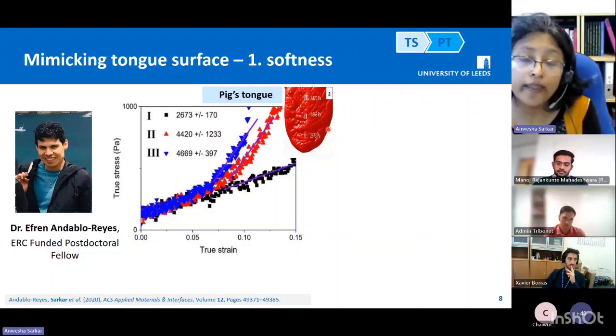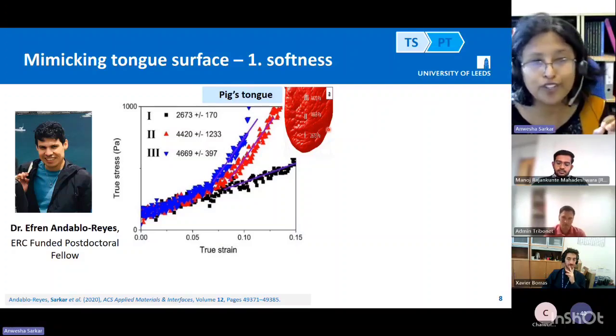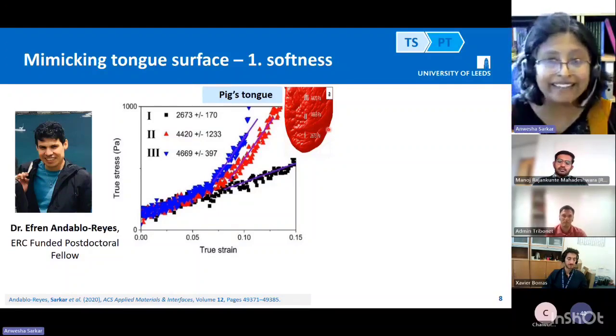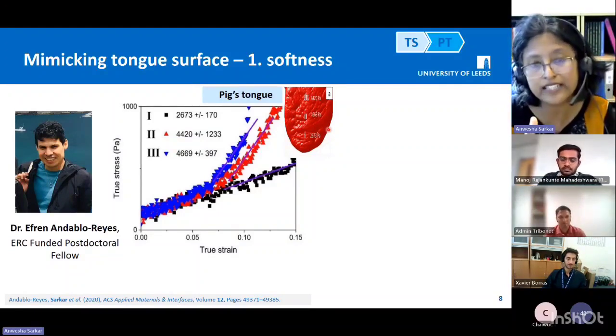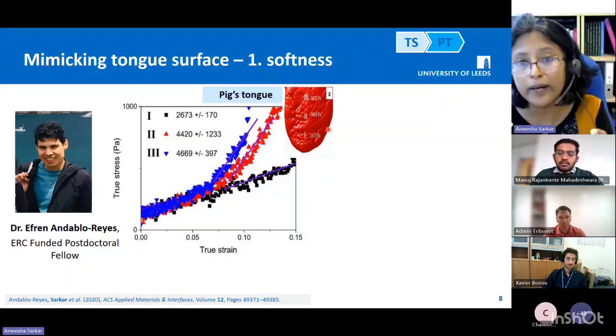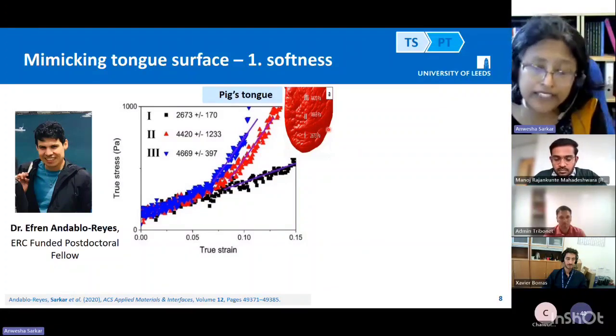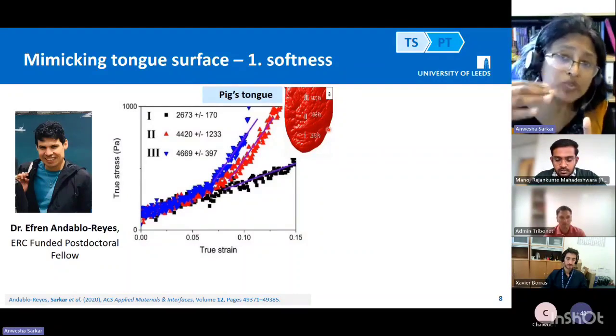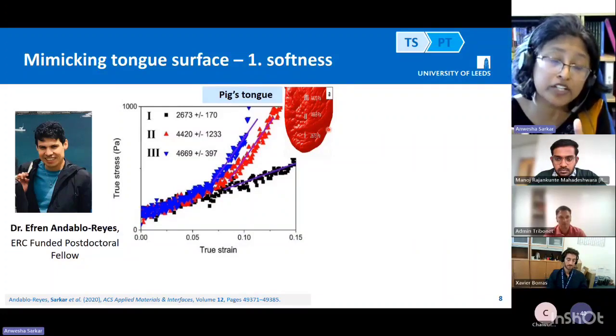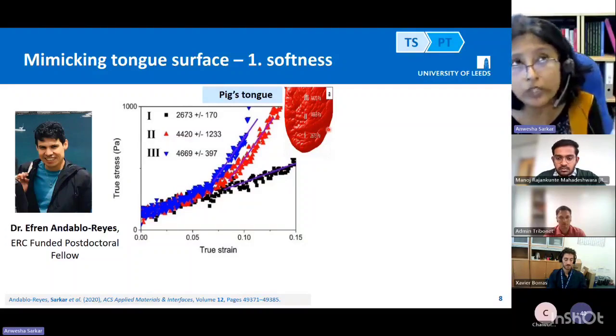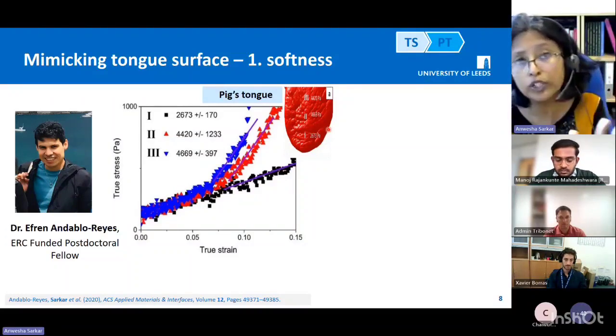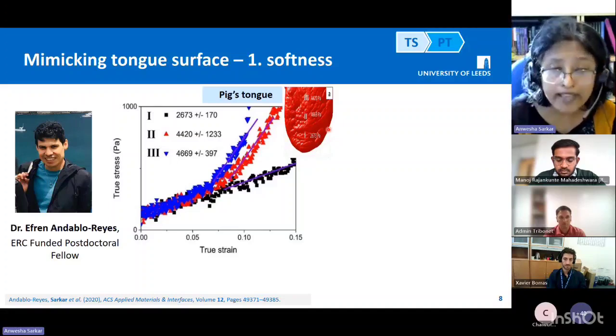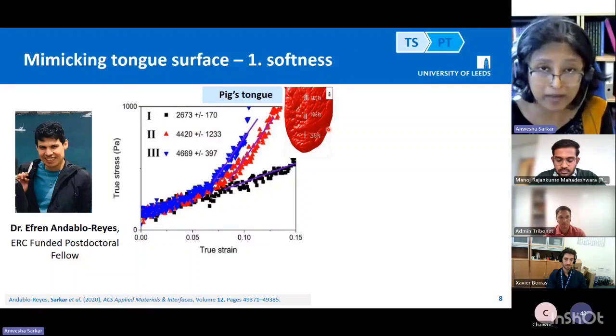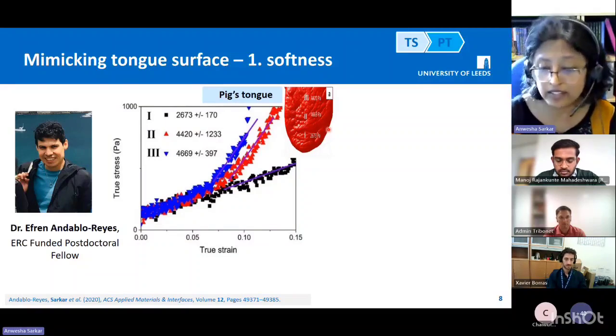But bear in mind one thing, this softness should be taken with a pinch of salt, because this is a dead pig's tongue, which has been extracted postmortem. But in a real human being or in a real animal, when you're eating, the tongue is a muscular organ. So it can actually increase in terms of the pressure and so on. So essentially, you're talking about roughly 2 to 20 or 30 kilopascal range, whereas your PDMS is in the order of megapascal. So that's where we are starting from.